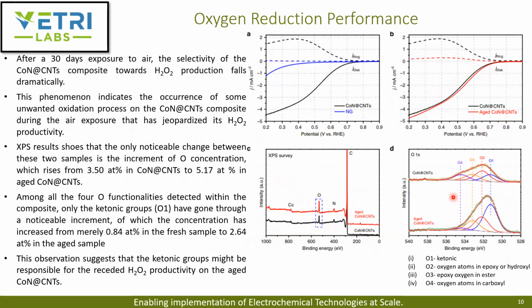So then, however, they start to get into trouble. So saying like, okay, what would be happening? So they exposed this cobalt nitrogen co-doped carbon nanotubes to air for about 30 days, and they called it aged CoN CNTs. And what they noticed, when they tested the electrocatalytic activity of that, is that the peroxide production falls drastically. And this indicates that there is occurrence of some unwanted oxidation process on the catalyst because it was exposed to the air, and that could lower the peroxide productivity.